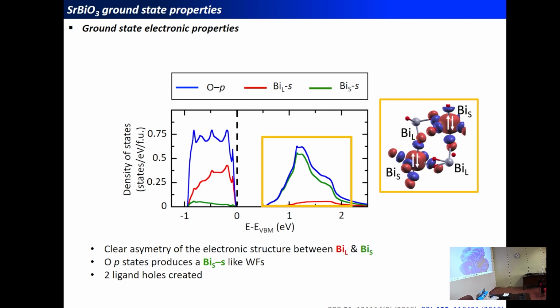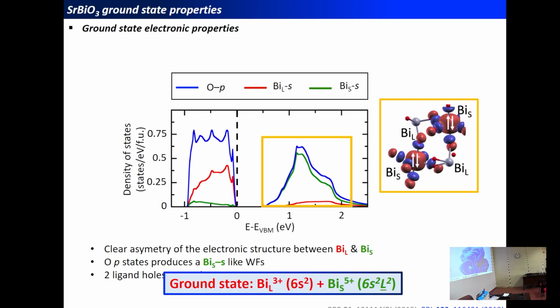And therefore, if we build the Wannier function associated with these unoccupied states, we end up with two Wannier functions that are centered on the small bismuth cation. And it does correspond, in fact, to a linear combination of the oxygen p states that give you the feeling that these bismuth cations have a S-like orbital, and these states are unoccupied. And therefore, what we create in these materials is ligand holes, and we have a ground state that in reality is described by a bismuth 3+ cation.